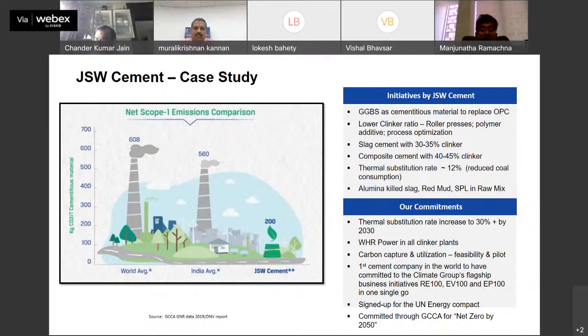There also, it comes to how we can utilize various byproducts from other sources to make cement production energy efficient. We have done clinker factor reduction phenomenally. We use almost 60% of GGBS in slag cement manufacturing and 35% of fly ash for fly ash cement manufacturing. Also, we are the pioneers to launch composite cement, which uses both fly ash and slag. This is our story of how we are efficiently able to reduce the carbon footprint.